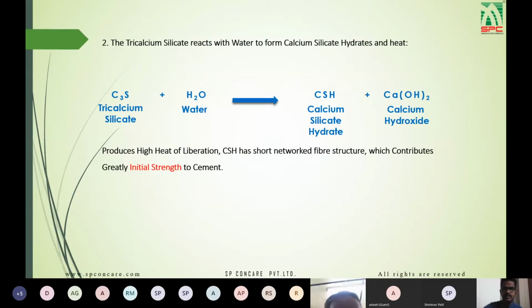So the next reaction is the reaction of tricalcium silicate with water. The tricalcium silicate reacts with water to form calcium silicate hydrates and heat. As you can see in the reaction, the C3S, that is tricalcium silicate, and water react to form CSH and then calcium hydroxide, that is Ca(OH)2. This reaction produces a high heat of reaction, and this is the fast reaction.